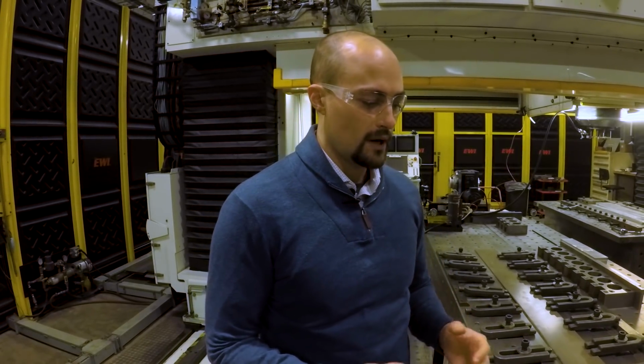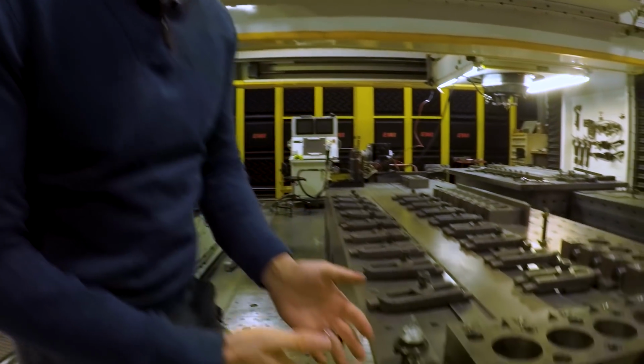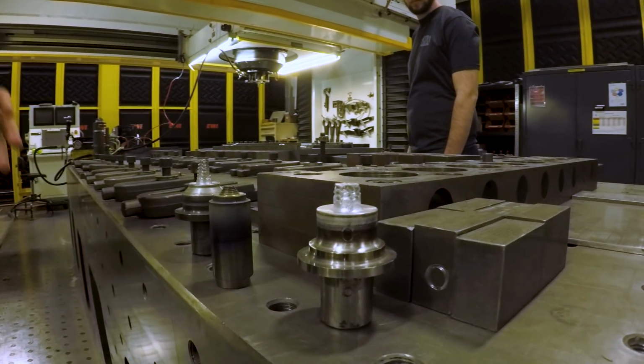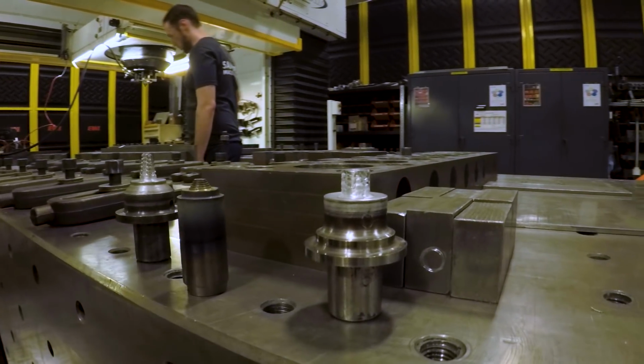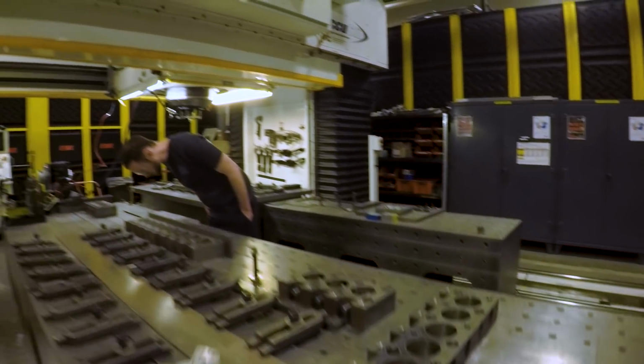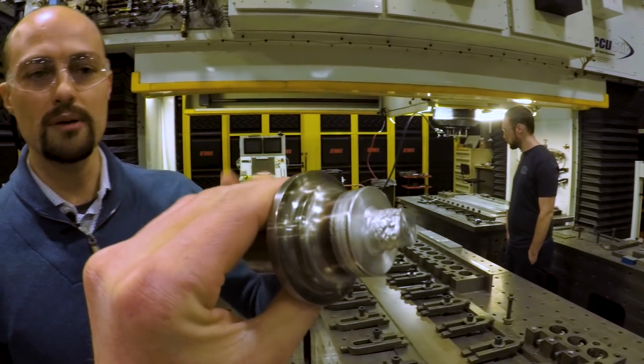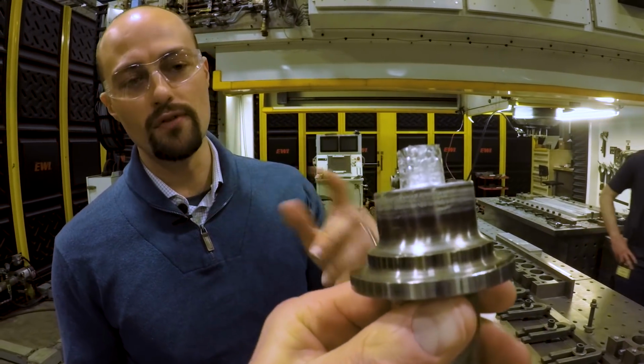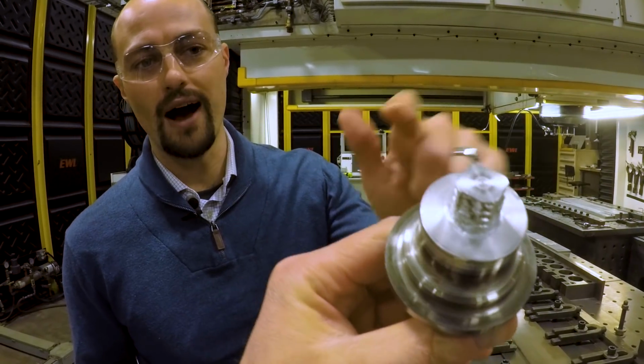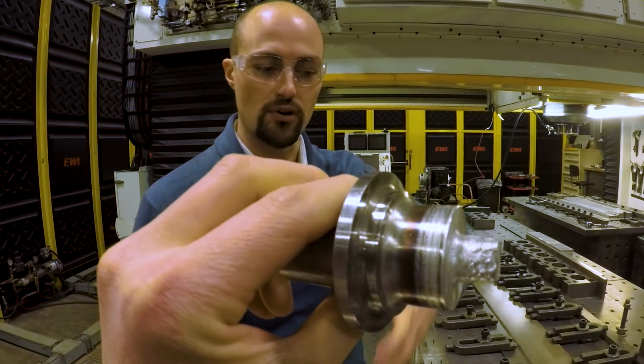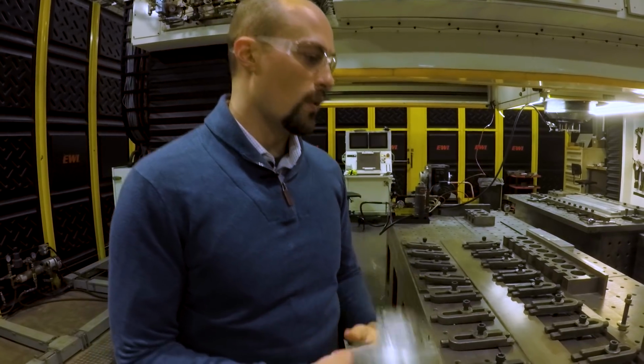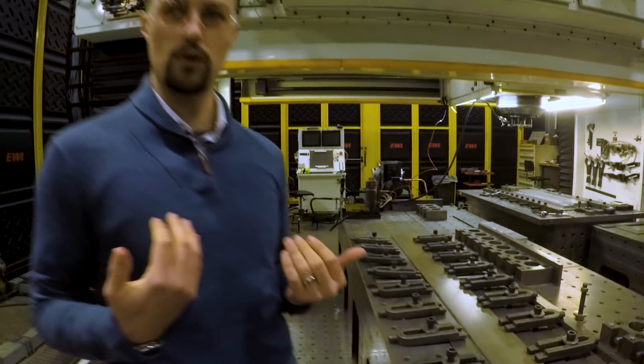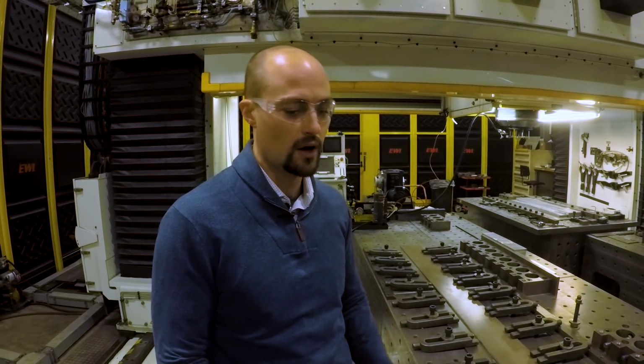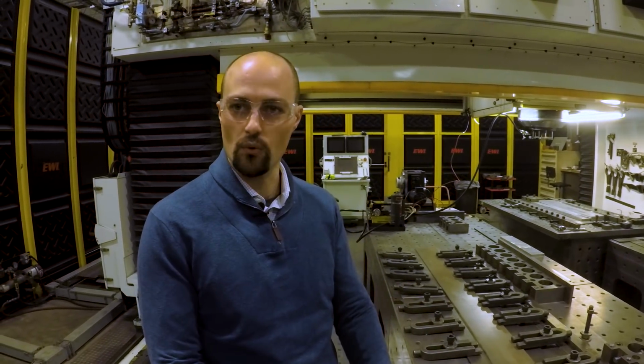Interesting. And as you can see right here, with the friction stir tools there is a wide variety, and this is kind of the black box and a little bit of black magic in friction stir welding. So this is an aluminum tool. Even though we have a little aluminum adhered to it, you can see we have threads and flats. The threads really help push material towards the bottom of the tool. You can design it to pull material up towards the shoulder or push it down towards the base of the weld. We find that pushing it down gives us better weld properties, and it really just depends on the chemistry of the aluminum what's going to be the right tool.